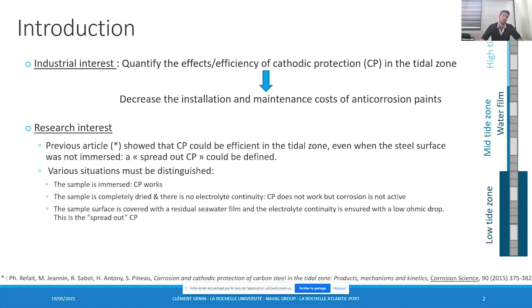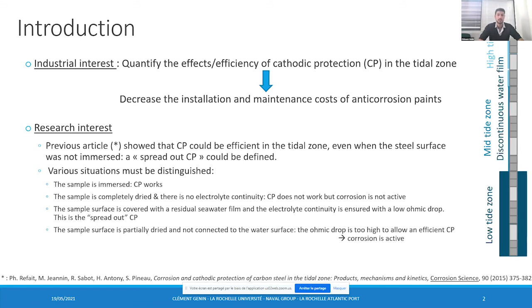Another case is when a water film is persistent on the steel surfaces, and then the ionic conduction is ensured, and the cathodic protection is ensured too. This is exactly what the spread out cathodic protection is. When this water film is discontinuous or too thin, there is no cathodic protection. So there is corrosion. Corrosion is active.